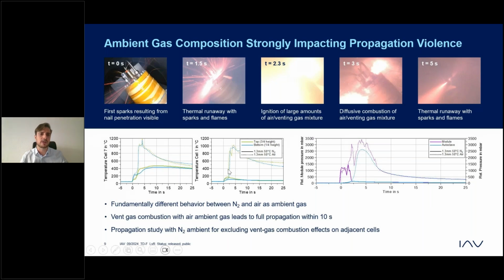If we look now to the next one, these are thermocouples which are placed in one of the neighboring cells. In this case it is cell number 1. You can see that in the air case we have a high increase in temperature, again as in cell 7, which is the central cell. So we are seeing here a thermal runaway of this cell, a thermal propagation from the central cell to a neighboring cell, which is not the case for the nitrogen case. So we see here that the ambient gas composition has a strong impact on the thermal propagation.